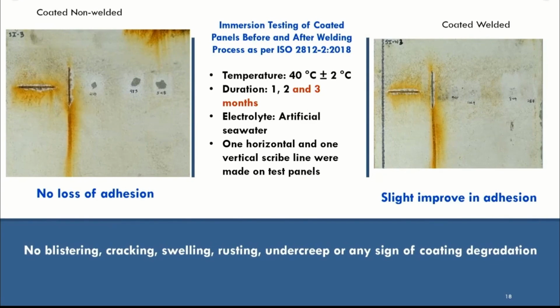perform. The two tests we have conducted that simulate actual field experience are the immersion test, where we did panels welded and coated, and panels coated, non-welded. We conducted the tests at 40 degrees C according to ISO 2812-2, and we removed samples after 1 to 3 months, okay? What we have done, we created an artificial scribe on the weld, and the same thing on the non-welded sample. The result we observed after 3 months is that there is no blistering, cracking, swelling, rusting, or under creep. There is no sign of coating degradation, okay?